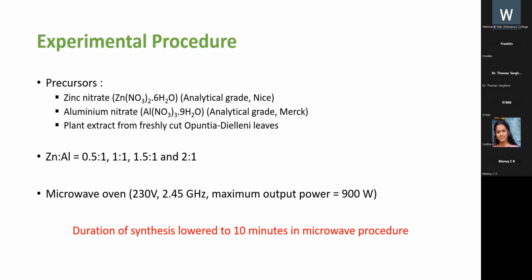Now we will move on to the experimental procedure of the present work. The precursors used are zinc nitrate and aluminum nitrate, which are mixed, and to that mixture a plant extract, the extract of freshly cut Opuntia-Dielleni leaves, is added, and it is heated in a microwave oven with these given specifications. I have prepared 4 samples with 4 different precursor ratios. The duration of synthesis is lowered to just 10 minutes.